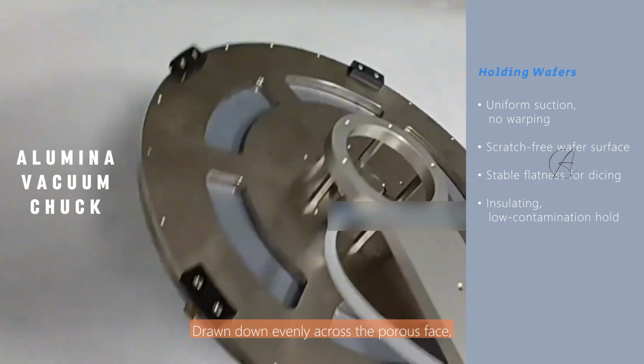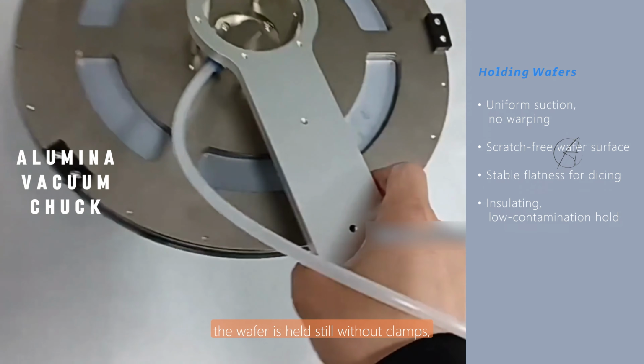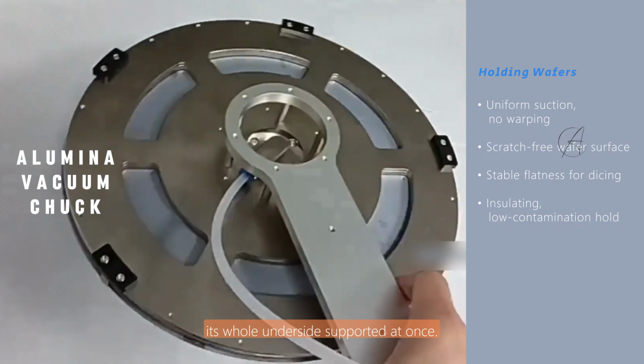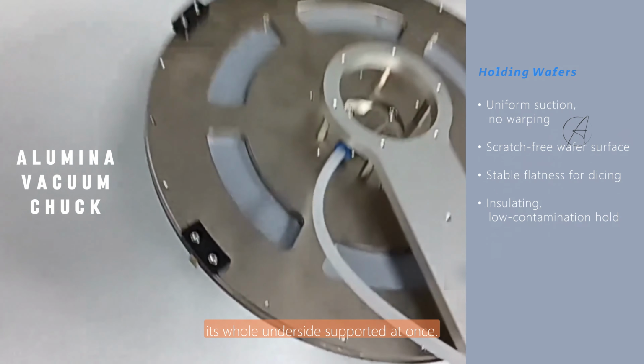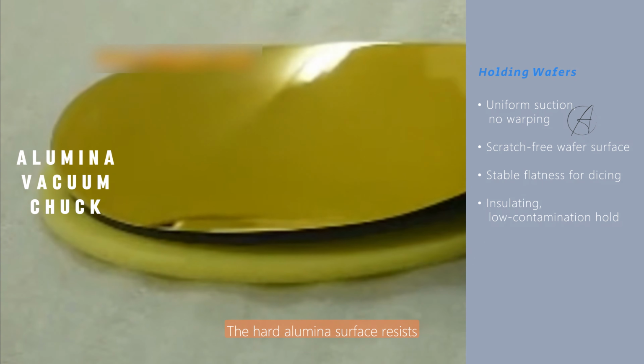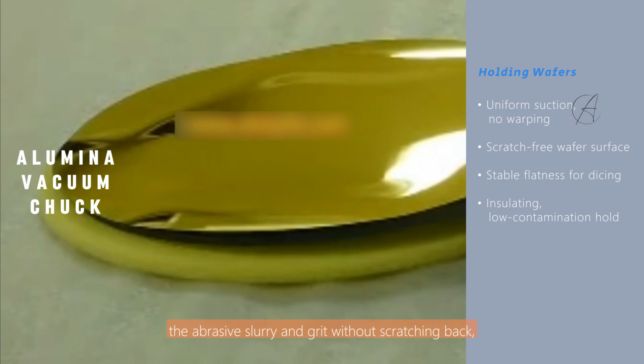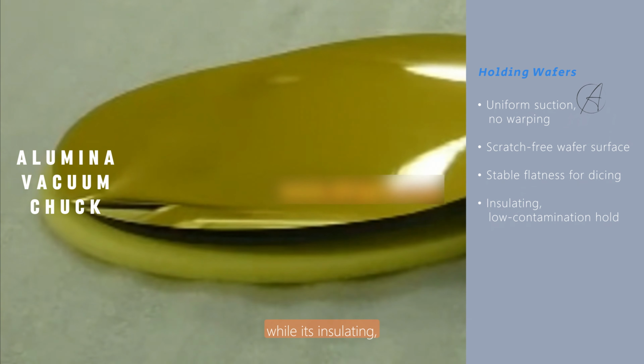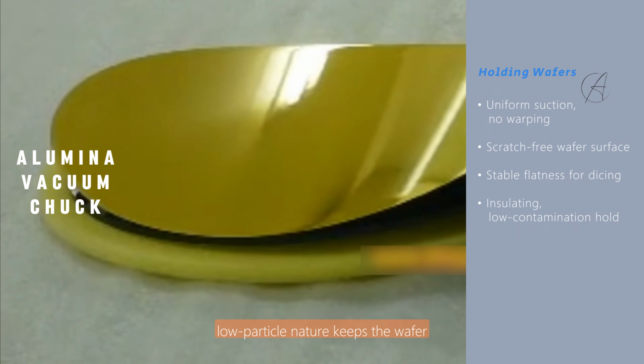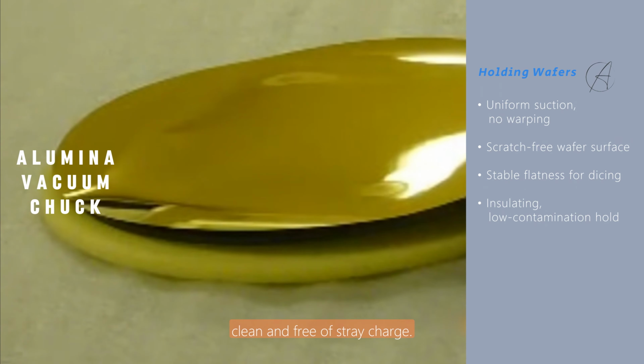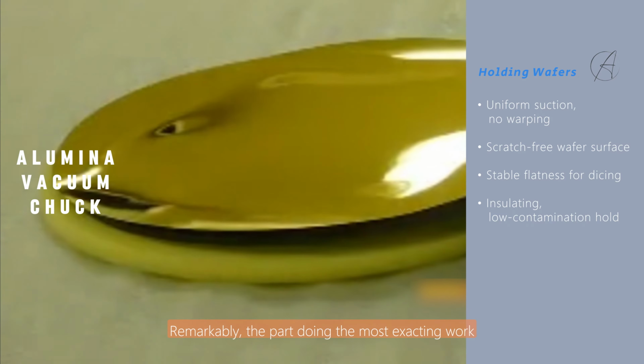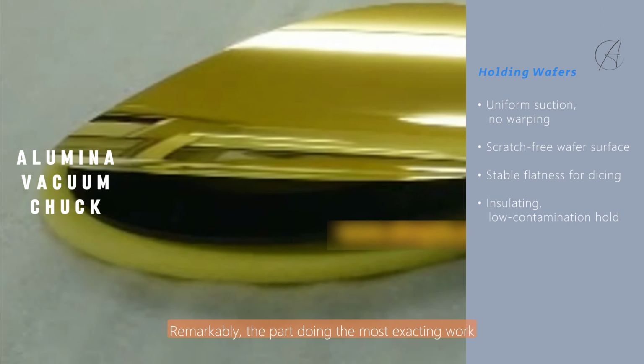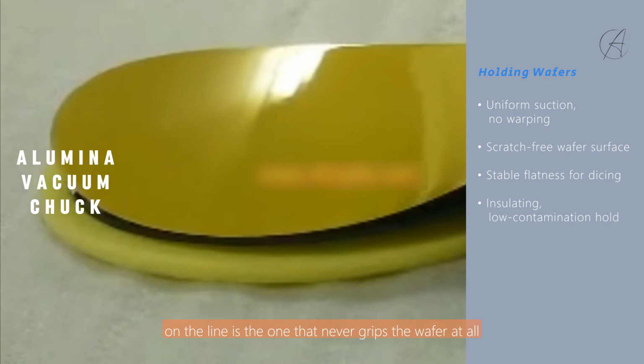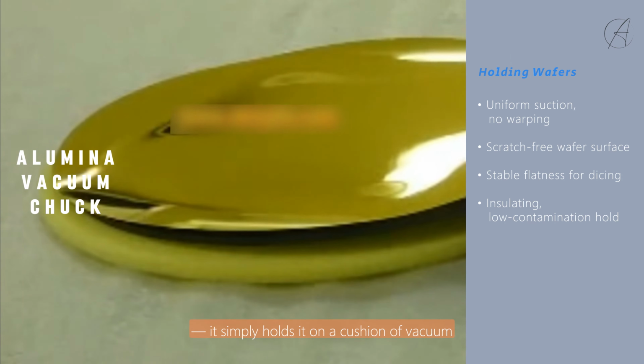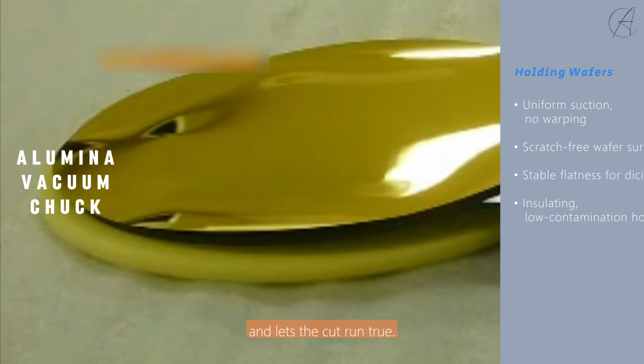Drawn down evenly across the porous face, the wafer is held still without clamps, its whole underside supported at once. The hard alumina surface resists the abrasive slurry and grit without scratching back, while its insulating, low-particle nature keeps the wafer clean and free of stray charge. Remarkably, the part doing the most exacting work on the line is the one that never grips the wafer at all. It simply holds it on a cushion of vacuum and lets the cut run true.